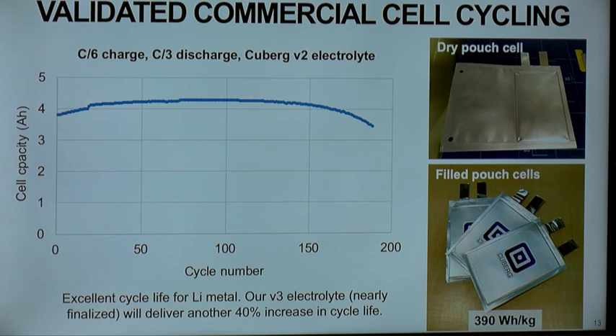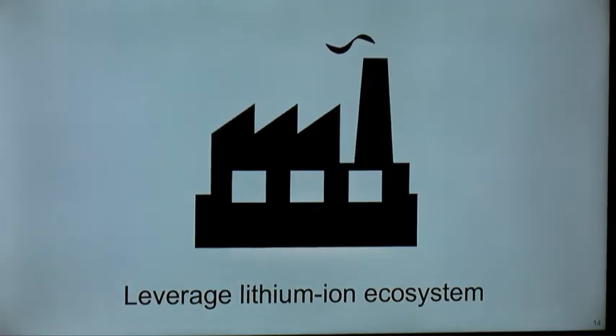In that commercial format, we're cycling it almost 200 times before it reaches end of life, and this is still with version 2 of our electrolyte. That's already quite close to U.S. Army standards for soldier batteries, which is typically 224 cycles. With version 3, we anticipate about a 40% increase based on early lab results, so we should already be there in terms of cycle life as well, which is one of the concerns the Army has had with our technology. So it's already enough for soldier power applications and validated with real cells.